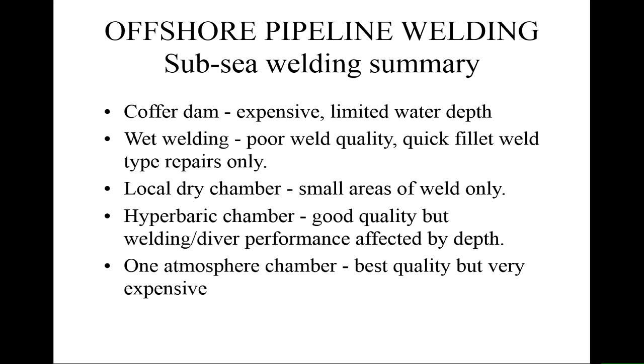You can run a welding torch underwater, but the quality of the weld is pretty poor. But there might be emergency cases where you would do that just to give you a short-term repair. Much better, if you have a small repair to do, is to use a local dry chamber, which you can clamp and pump the water out and just weld in that small volume. So for localized corrosion repair and things like that, that might be possible, but it's small size only.